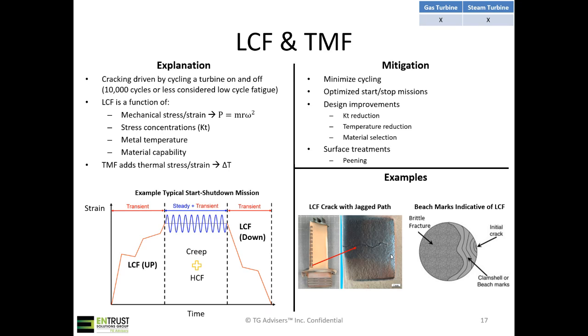In the bottom right-hand corner, we have a picture of a cracked blade. You can see that that crack is jagged in nature. That is a hallmark of LCF. Basically it'll grow at one angle or along a grain boundary, and then it'll stop. And then when you turn your unit on again, it'll start growing in another direction. So usually jagged cracks are indicative of LCF.